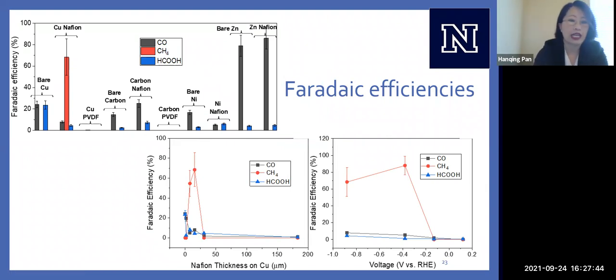We also wanted to test our polymer overlayer. Let's go to the extremes. Let's take an extremely hydrophobic polymer and let's put that on top of our metal and see what happens. And so we use this other fluorinated polymer called PVDF. And when we put down a thick layer of PVDF, it's completely shutting down our reaction because we're not seeing any products here, barely at all.